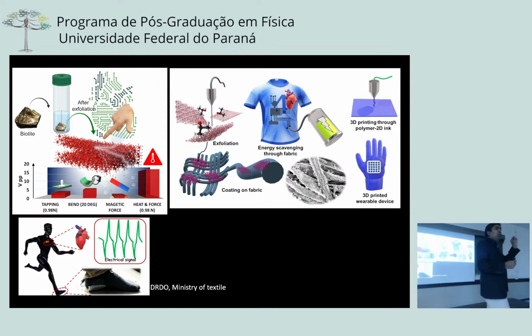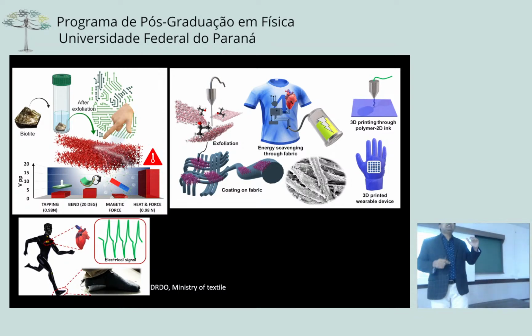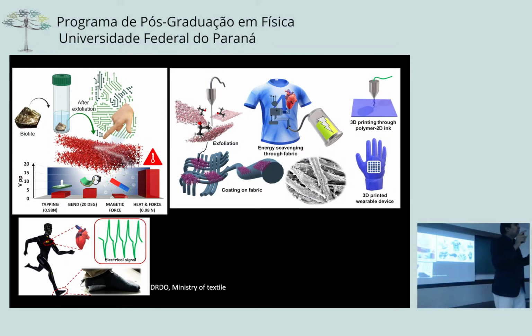What happens if you give a small amount of strain, stress or any force on the surface is that it's going to start having a change in charge distribution, which can be utilized to get potential, and that's what we do. A small amount of tapping or a small magnetic vibration or even heat can be utilized to produce voltage. This can be utilized for energy harvesting or for sensing as well, especially for health monitoring or any health-related sensing. Now with the 2D material, we can mix with cellulose for fabric and we can 3D print them, or we can even coat them and add this functionality to your fabric, right?